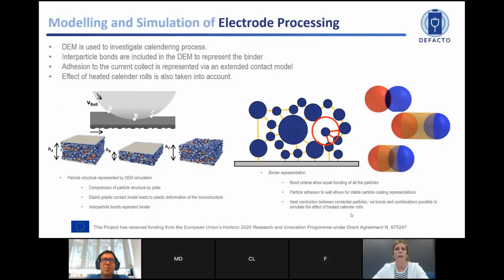So now we jump to the calendering. Once the microstructure is fixed, we apply pressure with a plate. What we do is use DEM models to investigate this calendering process. Here, we take into account the binder, which is represented by the interparticle bonds, and this is already included in the DEM. Also, adhesion to the current collector is included and is represented by the extended contact model. And also, the effects of the heated calender are taken into account. Taking all this into account, we are later able to, again, optimize the calendering step.